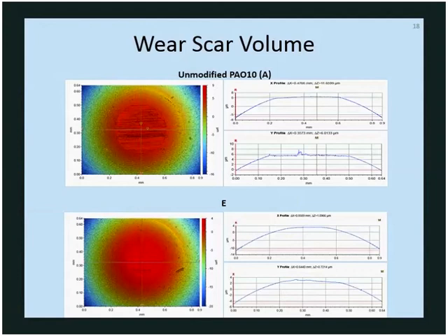And then this is just taking that ball that was done on ratio E and seeing the volume lost within it, and there's barely any volume lost compared to the one with the unmodified oil. There's a lot of volume lost, a lot of wear, on the system.